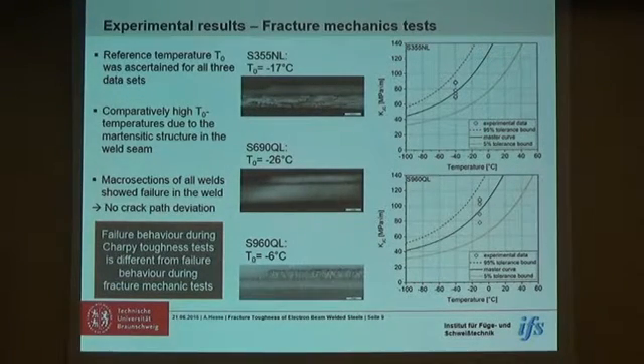The fracture mechanic test showed that all the specimen failed within the weld seam, so we didn't see any crack path deviation. We could ascertain the reference temperature T0 for all the 3 data sets. And if you compare this reference temperature with arc welded steels or base materials, they are relatively high.